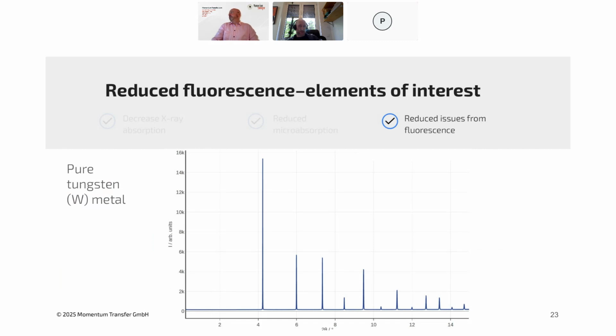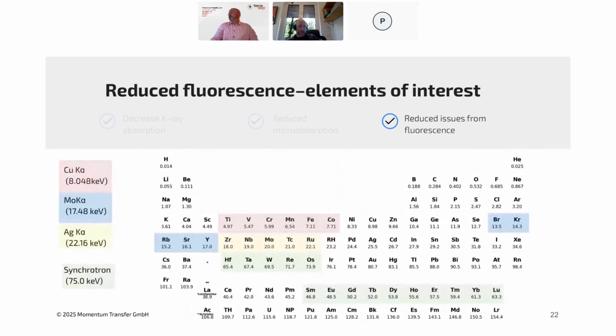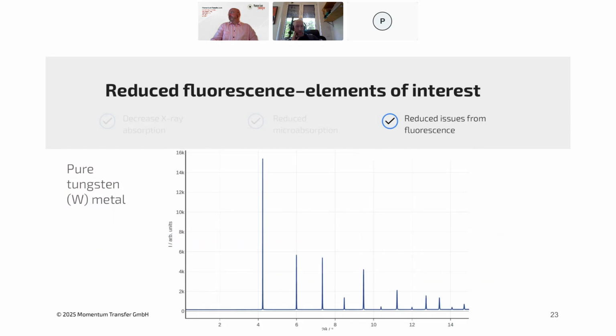And so as an example, I take pure tungsten metal here. So you can see tungsten is right in the middle of the ones that are closest to the problem area. And while we do have an elevated baseline of the sample, so all of your fluorescence scattering is underneath that baseline, it actually doesn't really affect the quality of the diffraction signal too much. So this has to be accounted for in phase estimations, but it doesn't significantly reduce the detection levels for having this kind of system, which is good.